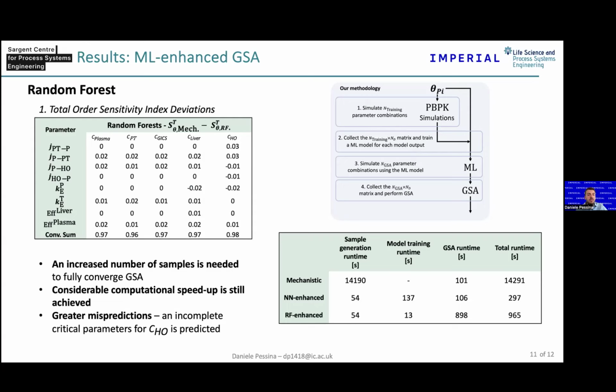Instead, if we look at the random forest results, the random forest has needed a few more samples to fully converge the GSA. So we had to go from 1 million and 200,000 samples to over 4 million samples with the random forest machine learning model. However, you still have a very considerable computational speed up that you can achieve. This is also because using the random forest to predict a single output, or in any case to perform a simulation, is much, much quicker than using the mechanistic model, because these are, again, as I said, very stiff and nonlinear models that are quite challenging to solve efficiently. We did see greater mispredictions in the sensitivity indices compared to the mechanistic model.